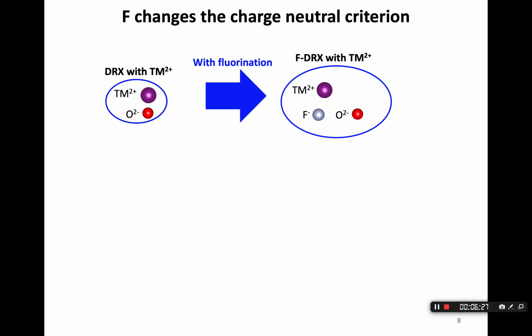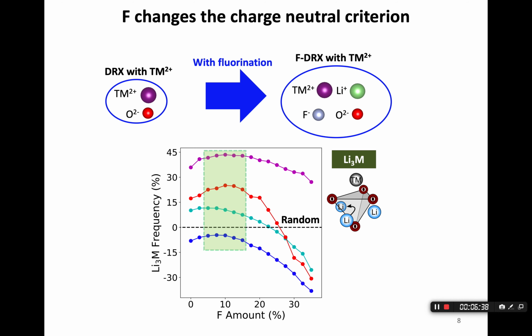In that case, it tends to attract lithium, and the transition metal will thus mix with lithium, so that you will create a lot of these 1-TM channels, which are made of lithium-3 and 1 transition metal in a local tetrahedron. So that is actually bad for the performance.